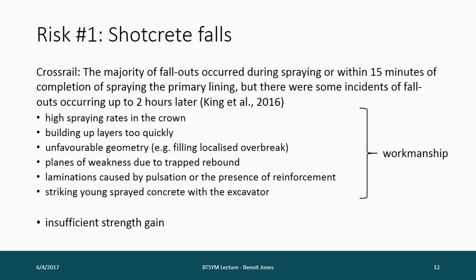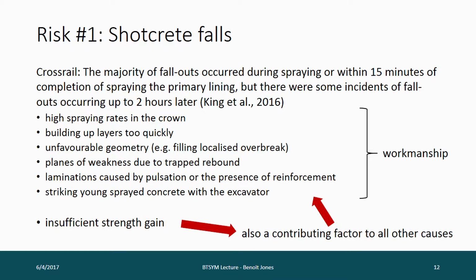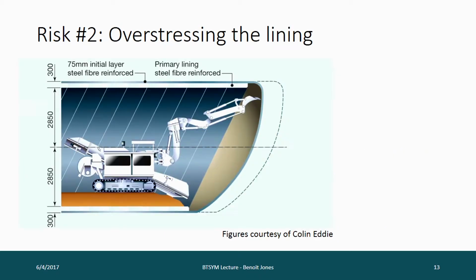And there's another possible cause of fallouts, which is insufficient strength gain. And if things like high spraying rates in the crown or building up layers too quickly, I mean, obviously, if you slow down your spraying or you make sure you build up layers more evenly and you don't just do the crown at the end and do the full thickness all in one go, then, in all these cases, having good strength gain is going to be helpful. Even if you've got quality problems like voids or planes of weakness in your shotcrete, if it's stronger, it's less likely to fall down. So, although workmanship issues have to be tackled, knowing what the strength is does give you some measure of mitigation of risk.